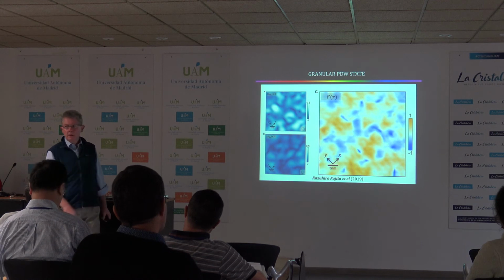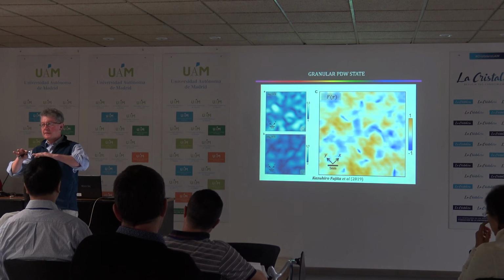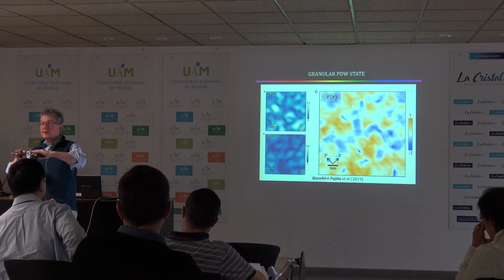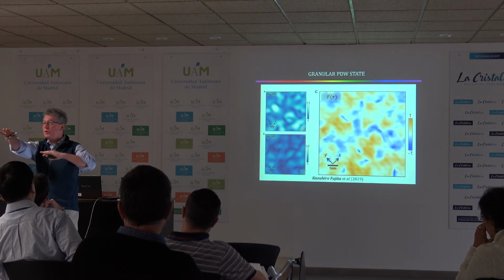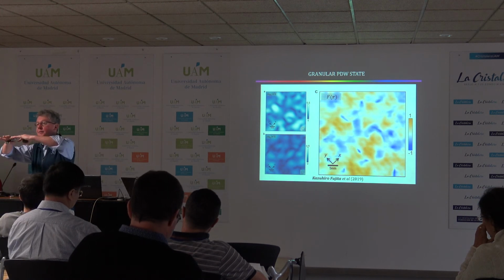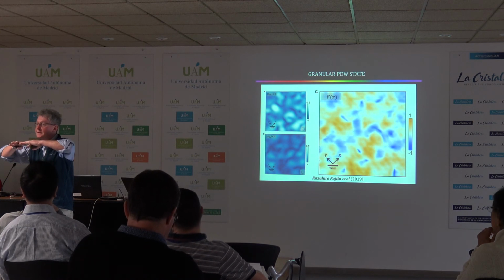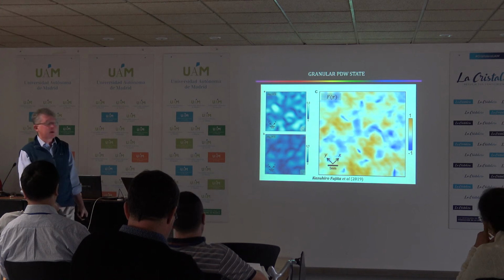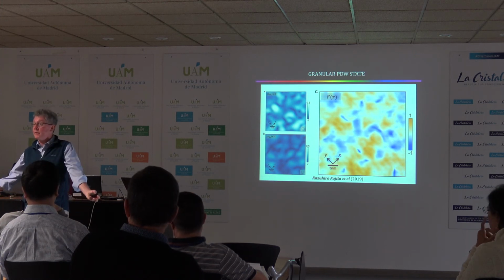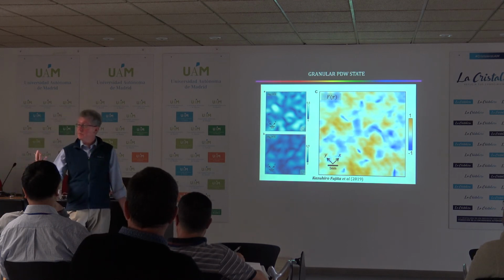But now with this observation, I start to realize that it's a granular superconductor, a granular pair density wave. It doesn't have long range order. It is actually quite susceptible to phase fluctuations, because there's no way to have a unidirectional pair density wave in one direction meet a modulating pair density wave at 90 degrees and have a net Josephson current, because the average over the phase differences is zero. So it might be that a granular pair density wave is just dominated by phase fluctuations. I have no way of proving this, but it's a new hypothesis that has come into my mind recently.